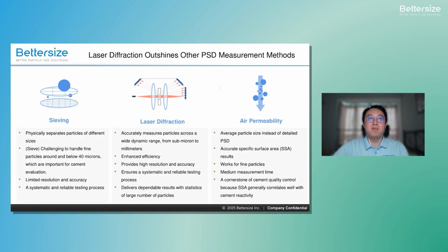However, the sieving method presents some challenges when dealing with fine particles, around 40 microns and below, and the resolution and accuracy of sieving results can be limited. As the only output of the air permeability method, the Blaine value brings some blind spots to quality judgment. Two cement samples can have identical Blaine values but exhibit divergent performance in concrete.